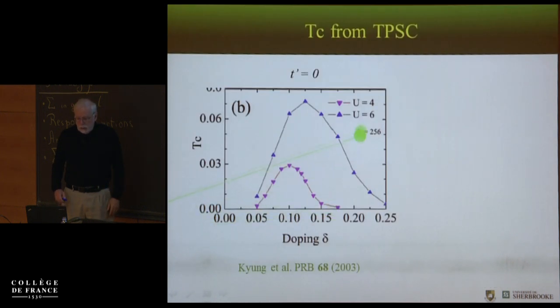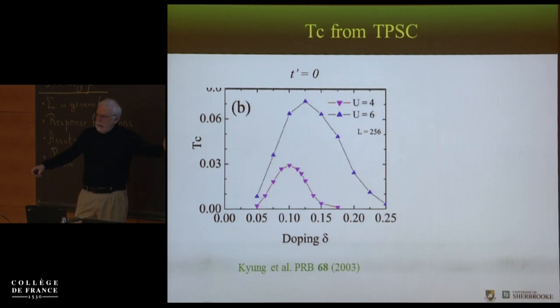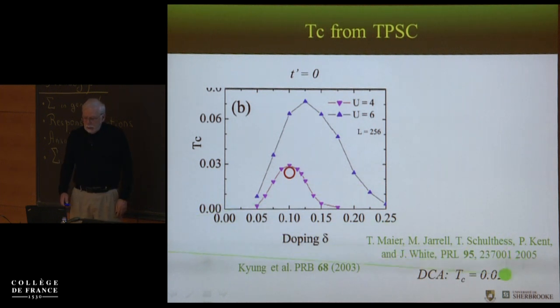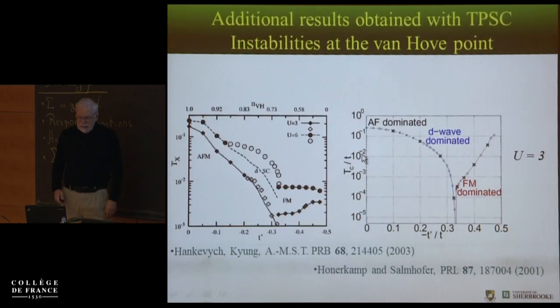And then what we get at U equals 4 is this dome for TC as a function of doping. And the reason it goes down is because of the pseudogap that's opening up. Now, I showed calculations from DCA that did many different system sizes and showed that there was a transition. I said it's the best calculation to show the transition. This is this 2005 paper from Jarrell's group. So they did the calculation at 10%, and they found TC is 0.023, which is in this region here of the red, and we have 0.029. So given that it's such a different calculation, it's not so bad.